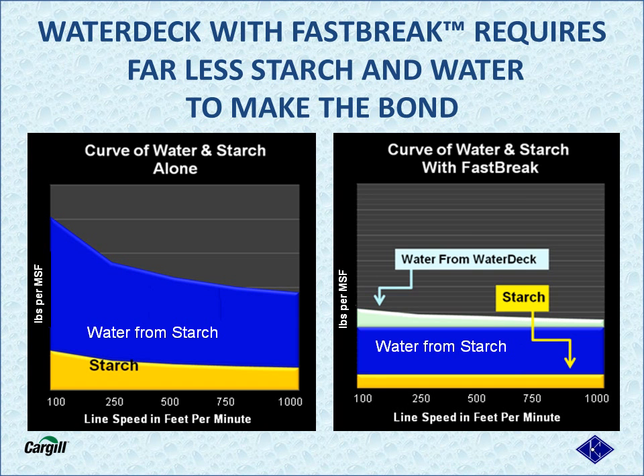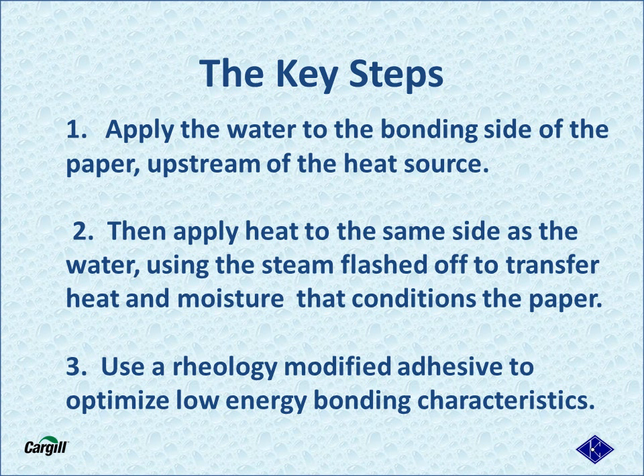If you take a look at these two graphs, they compare the curve of water and starch consumption on a traditional corrugator on the left and with an isothermal corrugator on the right. A traditional corrugator puts a lot of water and a lot of starch on at the lower end of the speed range. Isothermal corrugating enables you to flatline the starch at all speeds. Isothermal corrugating uses less total water during the entire process, and we adjust for the effects of speed and temperature by using the added control of the water decks. There are 3 simple steps that are involved. Apply water, apply heat to the side that you applied the water, and then apply a rheology-modified adhesive.